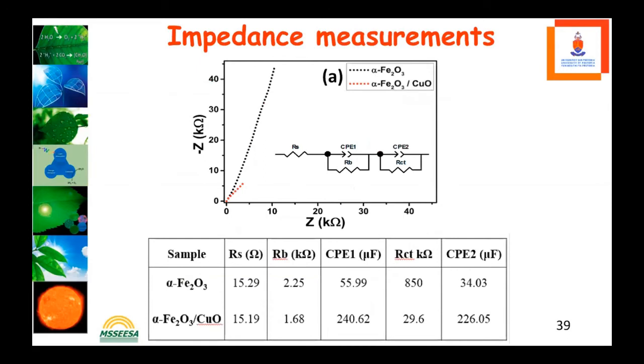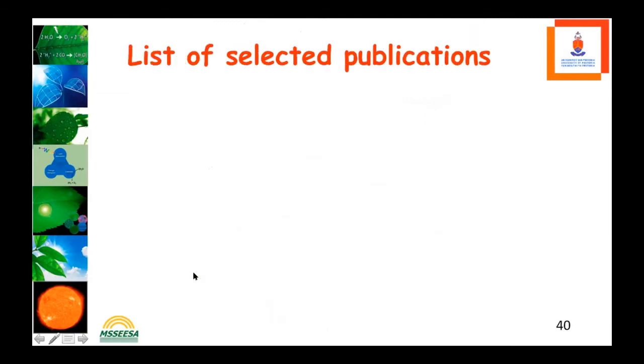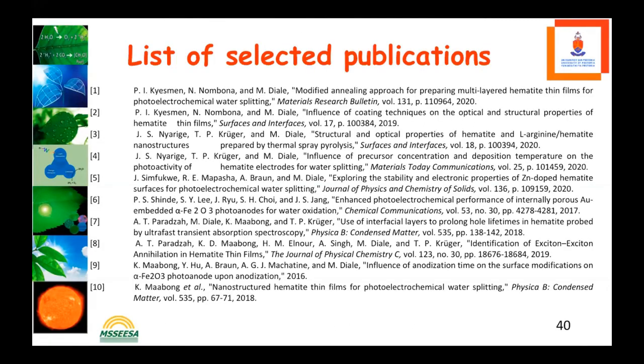All right, then we did impedance spectroscopy measurements where we're looking at the sample, the iron oxide and the iron oxide with copper oxide. And we found that the heterostructure gives better results than pure iron oxide. So we have published a number of papers from this work since we started some years ago. You can see that we have got up to 10 publications in our group,